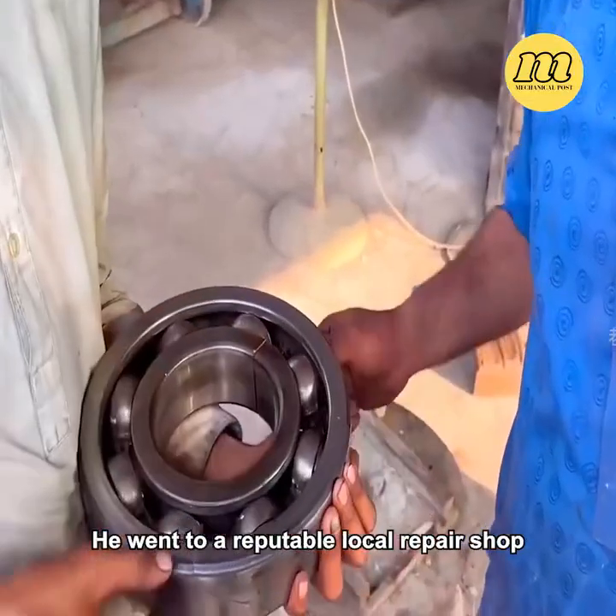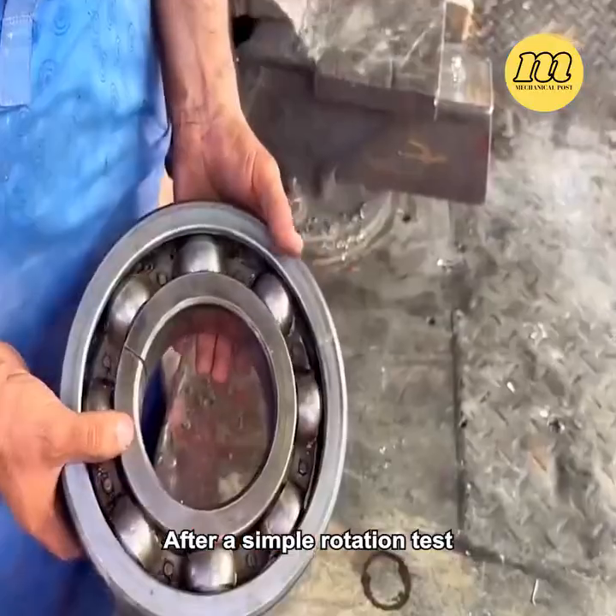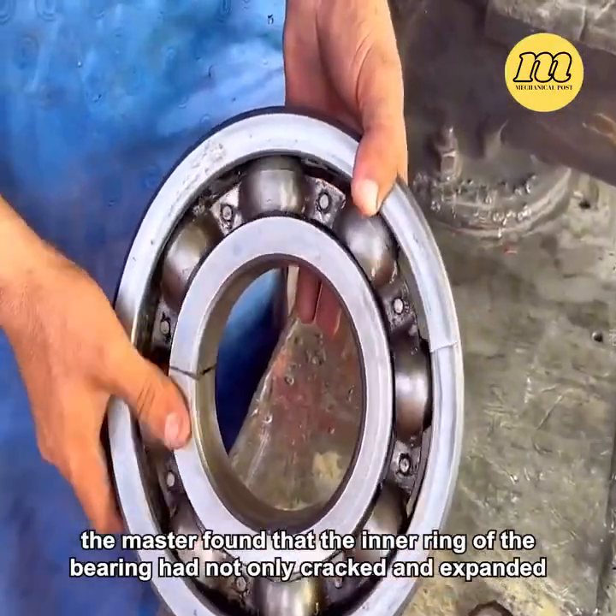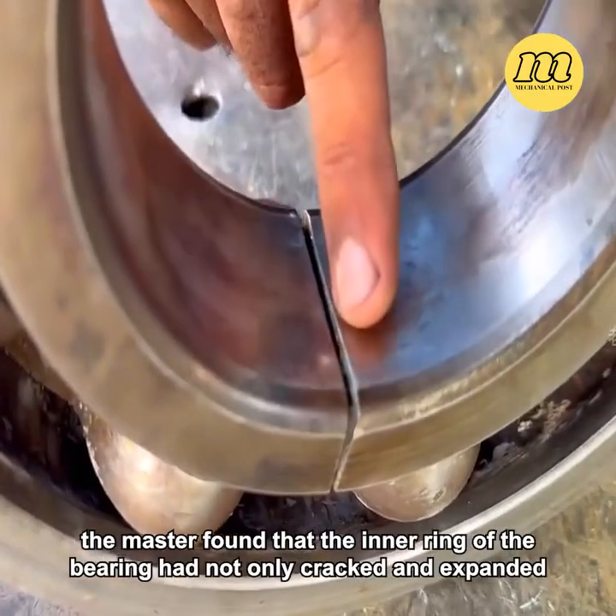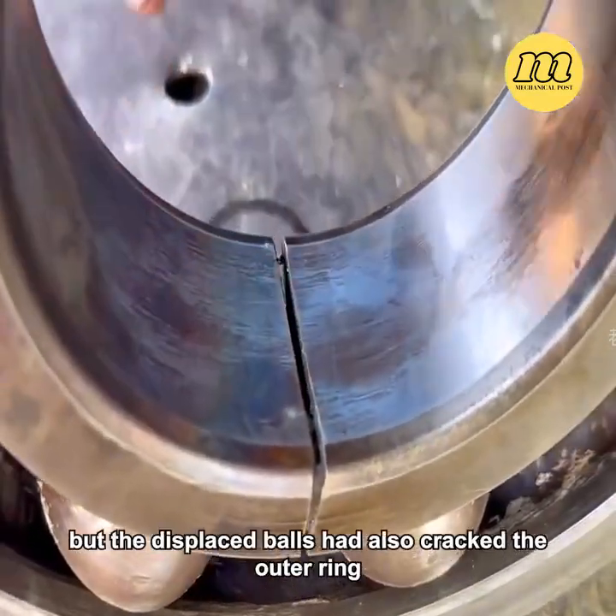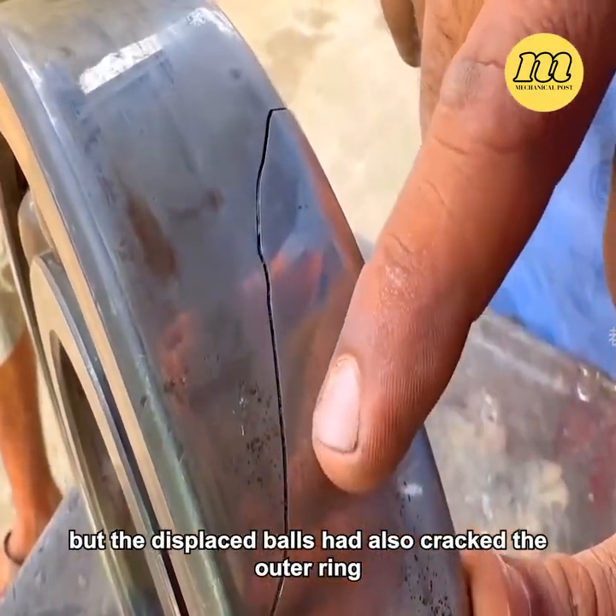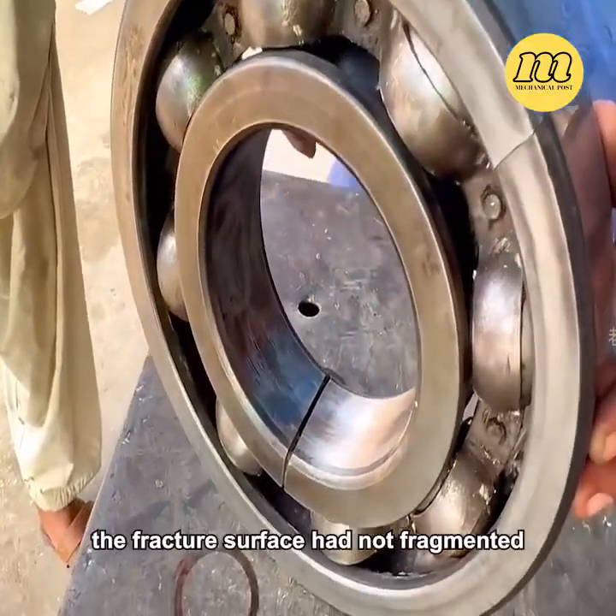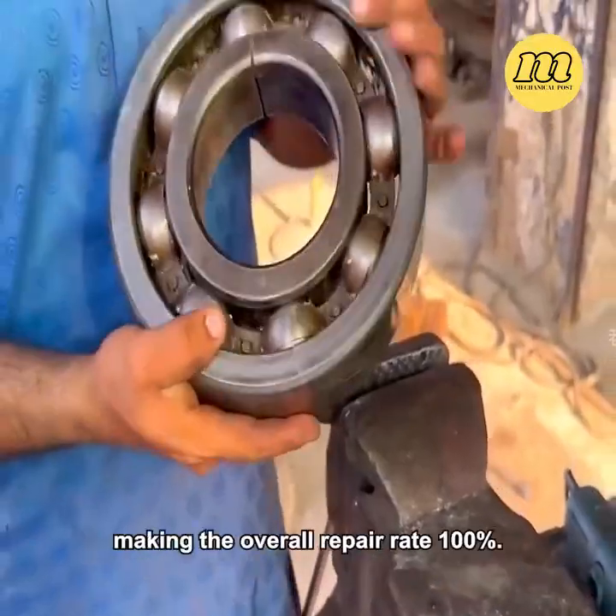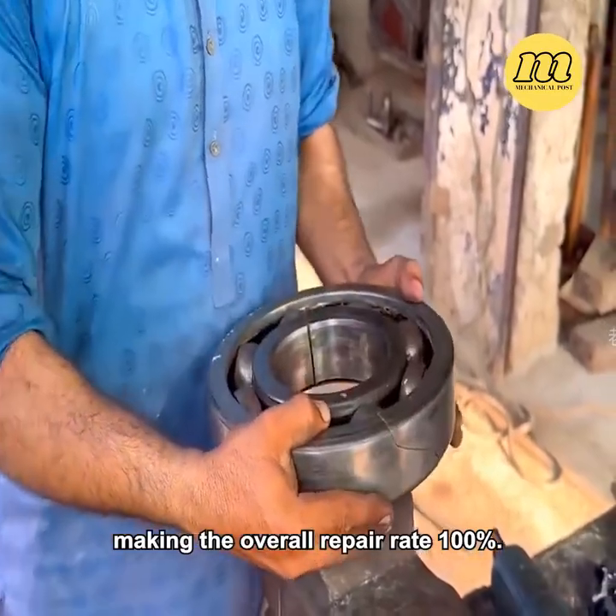He went to a reputable local repair shop. After a simple rotation test, the master found that the inner ring of the bearing had not only cracked and expanded, but the displaced balls had also cracked the outer ring. Fortunately, the fracture surface had not fragmented, making the overall repair rate 100%.